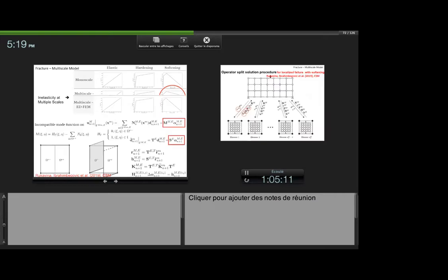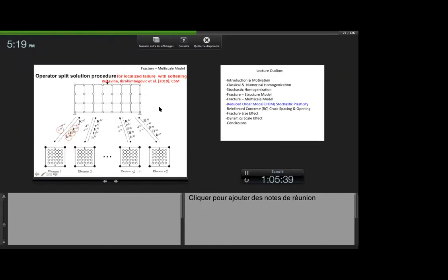Now, what you have to do is include at the macro scale another variable which is representative of this crack. In other words, macro scale displacements are not only tied to the macro scale displacement at the corner, to standard interpolation, but also to this discontinuity. And that gives you another type of connection between the micro displacement and macro scale displacement on the boundary. And once you run that, you have a perfect match between the monoscale computation with all defined scale and this multi-scale computation. Of course, that becomes a little more intensive parallel computation, but it's no big deal. You just have some extra variables to compute for every macroscale element.